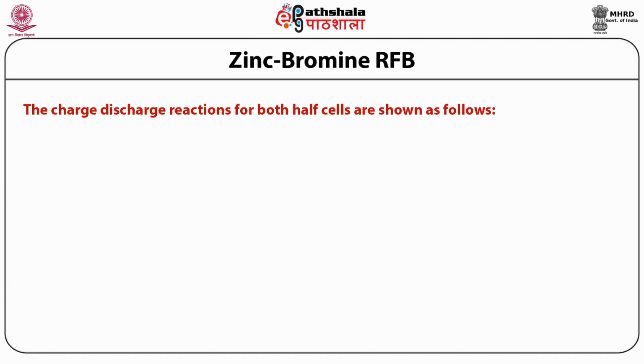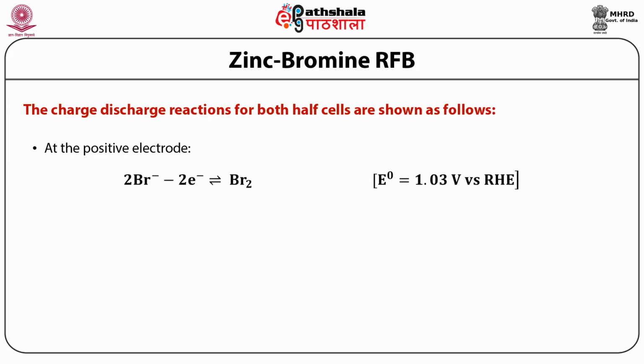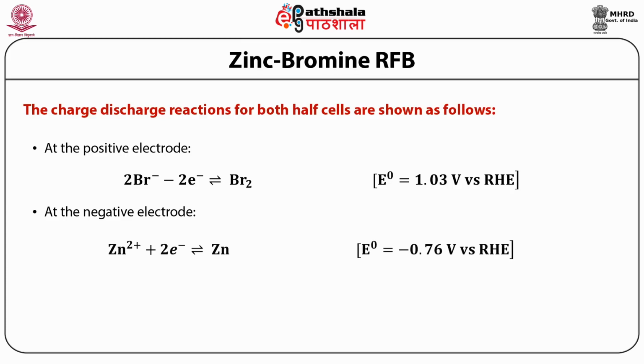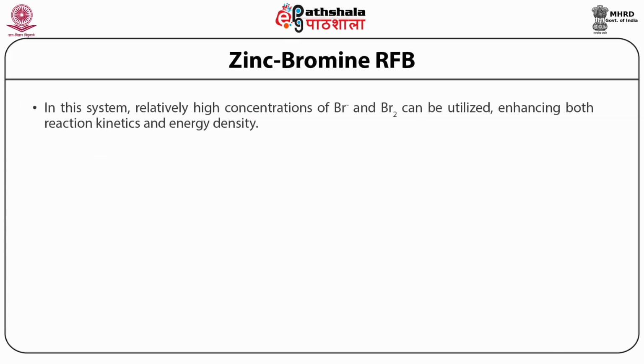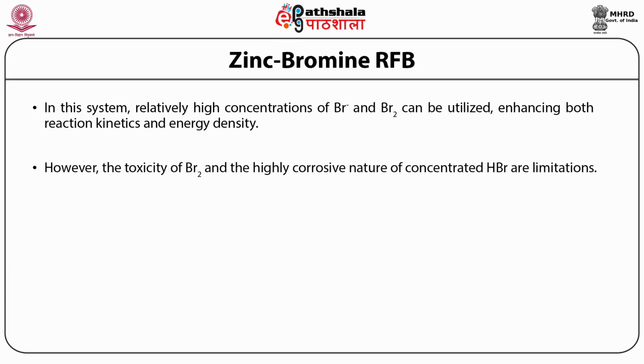The charge-discharge reactions for both half cells are shown as: at the positive electrode 2Br⁻ − 2e⁻ gives Br2, whereas at the negative electrode we have Zn²⁺ + 2e⁻ gives Zn. So the overall reaction becomes Zn²⁺ + 2Br⁻ gives Zn + Br2. In this system, relatively higher concentrations of Br⁻ and Br2 can be utilized, enhancing both the reaction kinetics and energy density. However, the toxicity of Br2 and the highly corrosive nature of concentrated HBr are limitations.